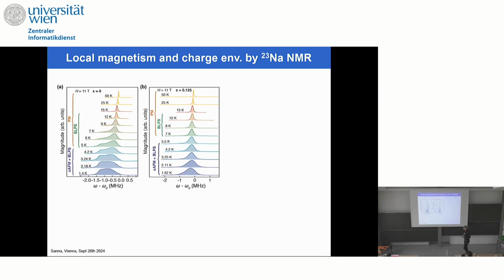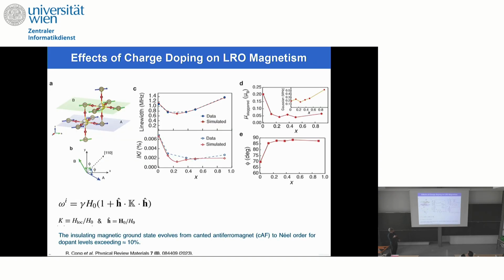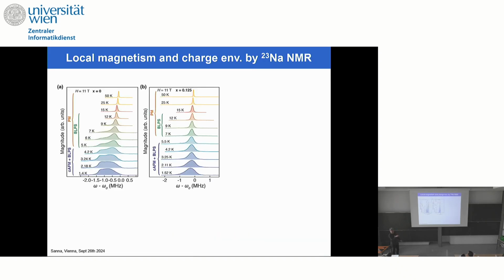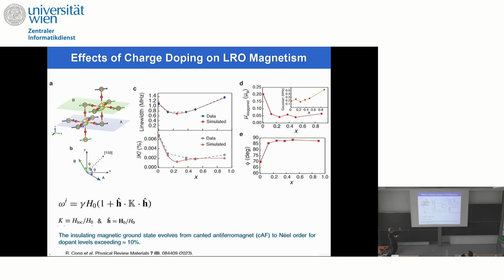Okay. What about the magnetic state as seen by NMR? In this case, the NMR spectrum for powders, with respect to the high temperature, where we have a very nice single line, is much broadened. And this is the same also when we dope the system, it is broader than at high temperature. We can analyze in very detail the line shape at low temperature here in the magnetic state,